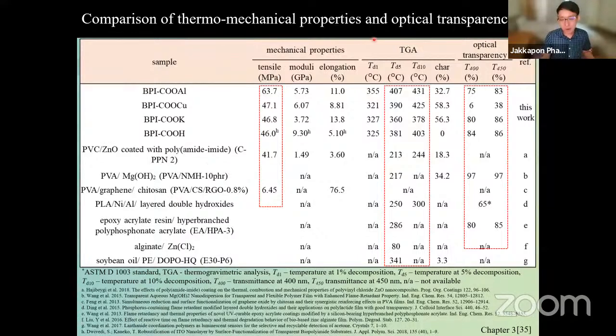Here is again mechanical properties, TGA, optical transparency, the thing that I want from my metal composites, right? The tensile strength here is quite good, 63.7 MPa. Not the best in the market out there, but it's good for some kind of film like this. We got TGA going up even to 400 degrees Celsius for BPI carboxylate aluminium, and transparency is about 83%. It can be used as a film, I think, but maybe just a little bit cloudy, not 90 or something and above. So here are mechanical properties and optical properties. Quite okay for me, comparing to the other study right here.